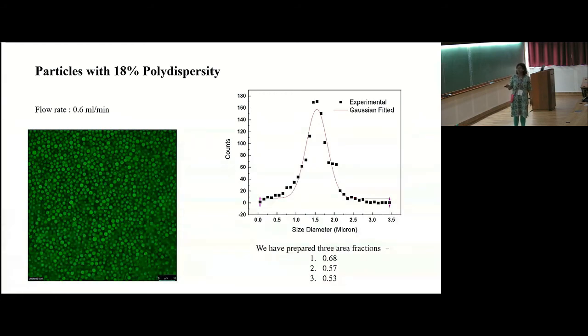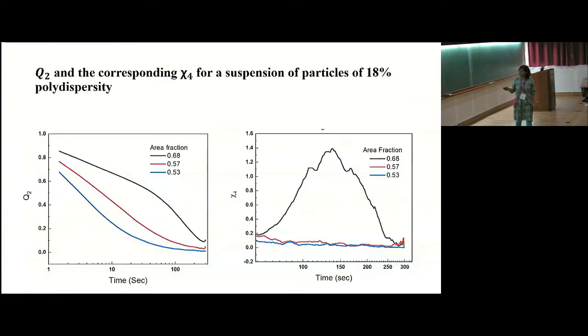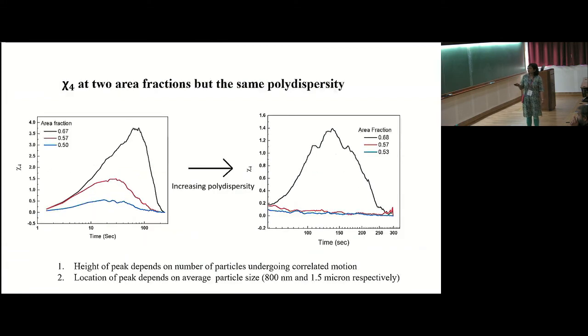We prepared similar area fractions again. And we see very much the same things. So again, here is the overlap function and you can see that as the area fraction increases, the dynamics become slower. The relaxation becomes more stretched. And when we use this data to calculate the chi-4, we find that the peak, so we see a peak in the chi-4 only for the largest area fraction, but upon dilution of the system, the peak goes away. So basically, the dynamical heterogeneities have disappeared and the system is fluidized.